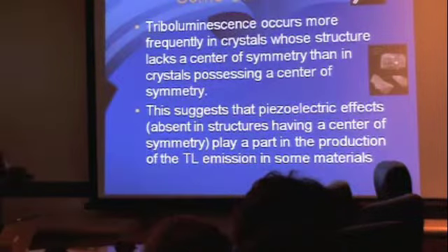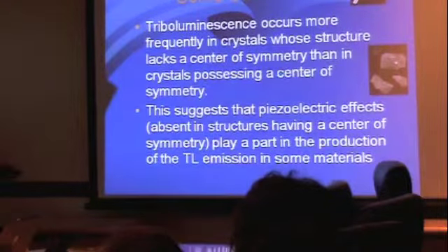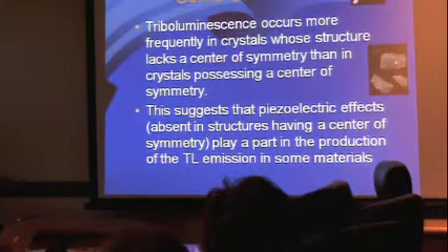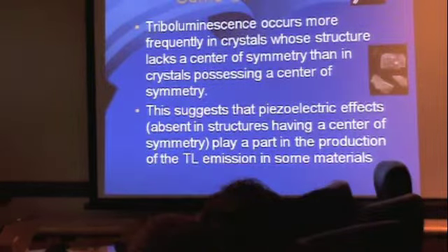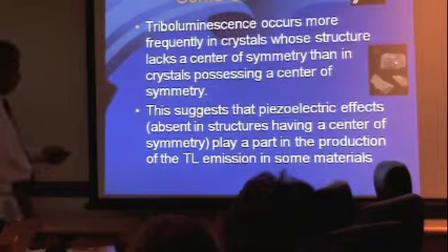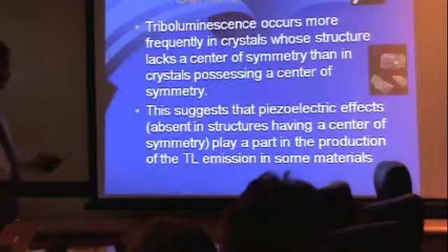We also saw that this happens more frequently in crystals where the structure lacks a center of symmetry. You don't see it in symmetric crystals. So anything which shows this has to be a non-centrosymmetric crystal. For any crystal, we check whether it is centrosymmetric or not.